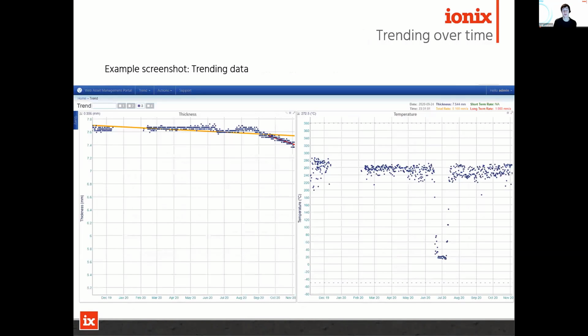The trending is really useful because it allows you to determine things such as corrosion rate, and it allows you to see changes. So we can overlay corrosion rates onto these. So a total corrosion rate or wall loss rate, because I suppose you don't really know if it's corrosion or erosion. But also change the period you're looking at, so look at short term, long term, for example.